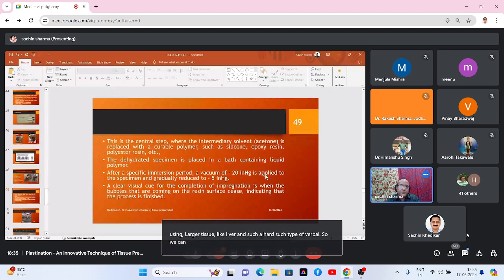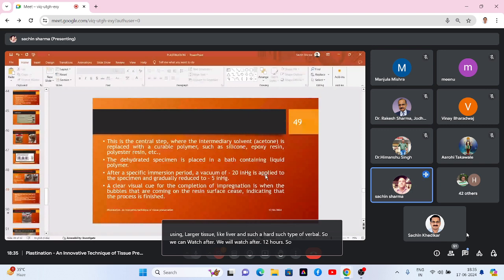we will watch after 12 hours, so that the resin will properly insert inside the material or specimen. A clean visual view of the completion of impregnation is when the bubbles that are coming on the resin surface cease. As we have told you, acetone will come out in the form of air bubbles. So when it ceases, it indicates that the impregnation process is finished.